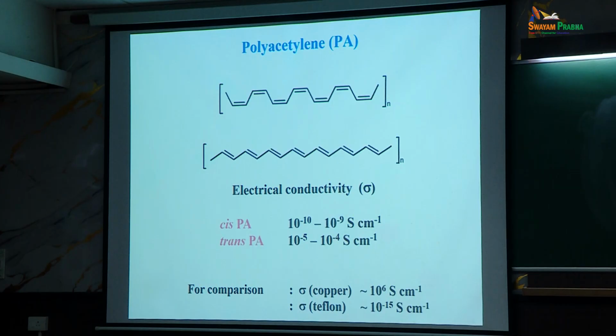When they analyzed it, they found they were basically polyacetylene. So these are two different isomers of this, completely trans or completely cis. And the electrical conductivity of these are not very good. They are very, very low, as you can see, compared to copper. I showed you this chart earlier. Copper is 10 power 6 approximately. Teflon is 10 power minus 15. So these are somewhere in between, but not great conductivity, not like any metal.